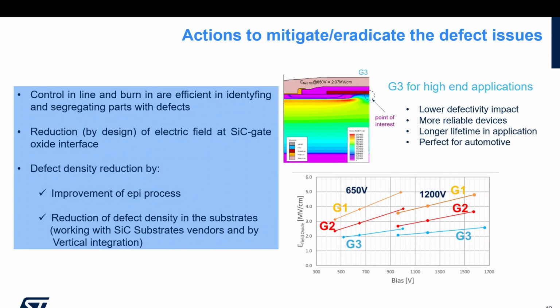Having said that, of course, how do you cure this? It's very simple. You do some material study in order to get to better and better substrate and EPI. You also make a design for manufacturing. So moving from generation 1 to generation 2 to generation 3, we have modified the structure of the device so the electric field at the interface between silicon carbide and gate oxide is progressively smaller and smaller. Typically, in a gate oxide, reducing the maximum electric field by 1 megavolt per centimeter gives you 2 orders of magnitude in the lifetime of the gate oxide. So it's important that you do this.